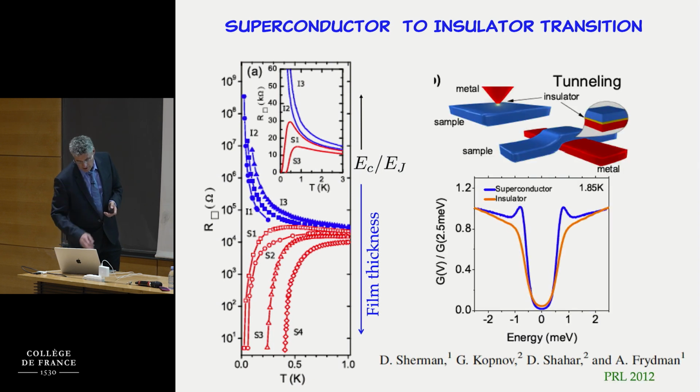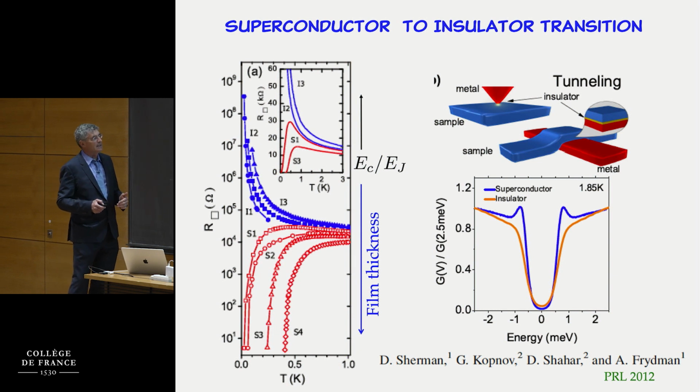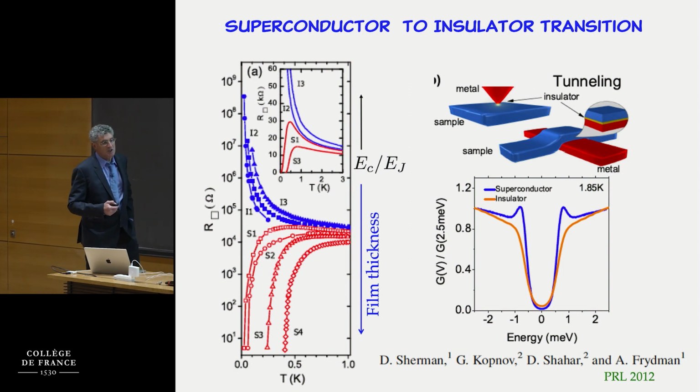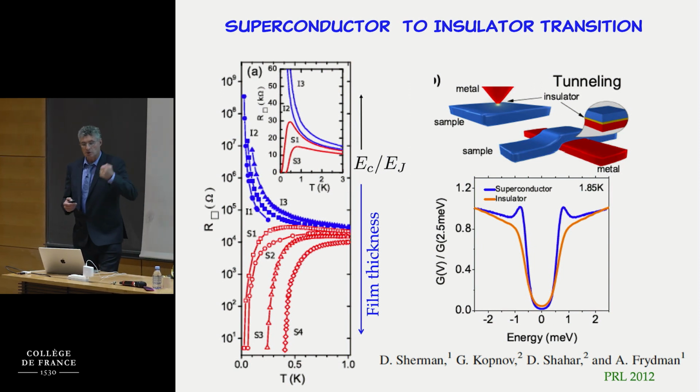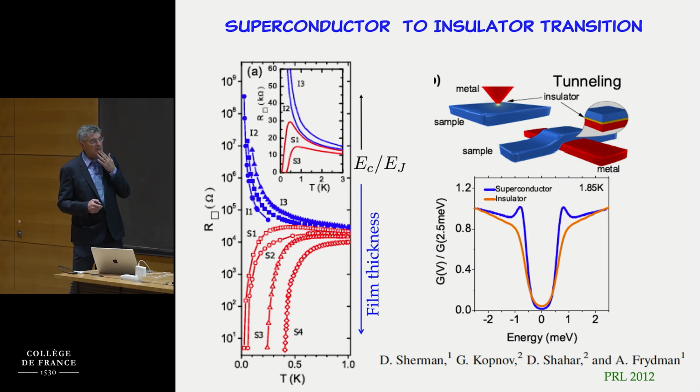However, in order to show that the quantum critical point is bosonic, they also had to do an experiment showing that the gap to break a pair doesn't change between the superconductor and the insulator. Because one of the options for an insulator was an Anderson insulator, where essentially you talk about free electrons in a strong disordered potential, and they localize. However, there seem to be no free electrons here if the gap doesn't close, because this is also a bosonic insulator,